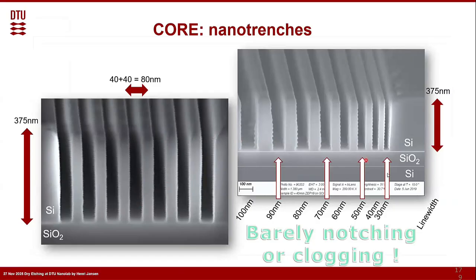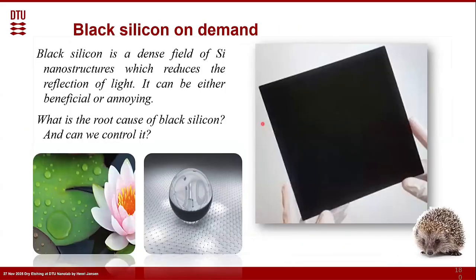You can go down to the very small scale, like here, 30 nanometers, and you can still see the scallops, but they look cool and they look okay down to the smallest level. It has also, in this case, no what we call notching. I will not go into detail, but that's also something which is not pronounced for the core process. And now I tipped it a little bit, and that's black silicon. That is the roughness which is sometimes created on wafers, and some people like it and some are annoyed by it. Now, first, what is the root cause of black silicon, and can we create it?